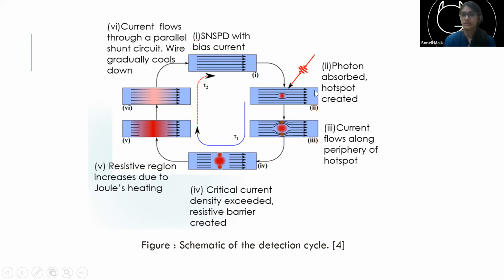No continuous Joule's heating, so it will cool down, and then the next cycle starts. Then again, the current which has gone through the shunt circuit will start flowing from our SNSPD once it becomes superconducting again, and it can absorb the next photon. So was that clear? Yes.